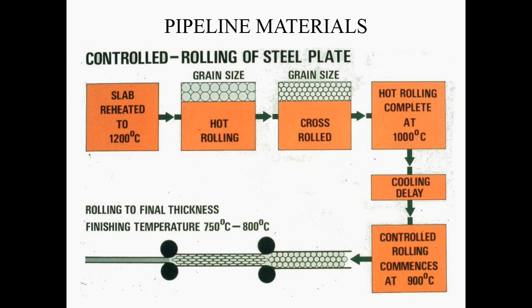So we start off with this grain size here, and we put it through a couple of rollers, and you can see the rollers reduce the size. These approximately spherical grains get elongated in the rolling direction. And then there's another roller here, and then even smaller grains, again elongated in the rolling direction. So hopefully, by the time you get to the final thickness, various steps of rolling have taken place, and the temperature is around 750 to 800. So about a 200 degrees C drop for both hot rolling and cold rolling. So that's what you're trying to achieve. And to do that, the grain size is much, much smaller than the hot rolling case. And that's the key point to getting the good properties for this material.